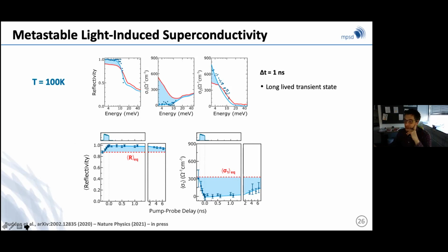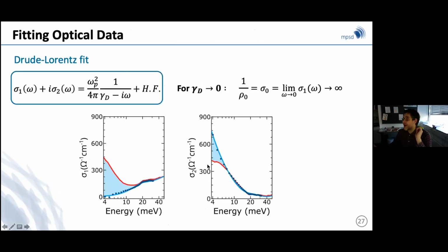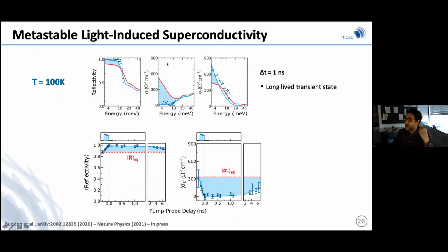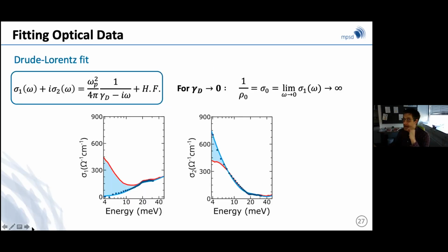Okay. The second thing that I can say is that what one can do is now start thinking whether one can do the same experiment by directly measuring electrical transport and observing a zero resistance state, as a precursor to maybe doing more sophisticated measurements that involve magnetic responses, maybe even tunneling, and other features that are proper of equilibrium superconductors. So just to look at what we can expect, we can take these data that I have shown you, and I can apply a Drude model. I can just run an unbiased fit, whether this is a superconductor or not. I can extract the zero frequency conductivity from the Drude-Lorentz model. Basically, this is a signature of the superfluid density or of the carrier density.